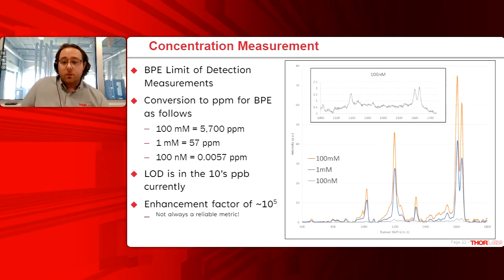The last characterization we ran was for concentration measurements, or limit of detection. So in this case, we used BPE again, and we went to smaller and smaller concentrations down to around 100 nanomolar. That's equivalent to around 5.7 parts per billion. And you can see here that even at 100 nanomolar, we still see the characteristic peaks of the BPE molecule, indicating that our limit of detection can be somewhere in that parts per billion range.